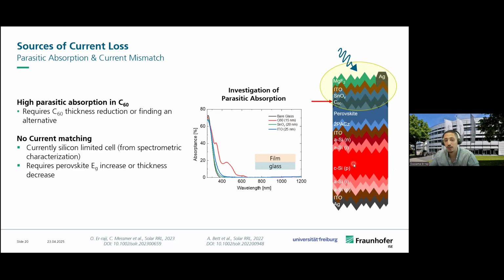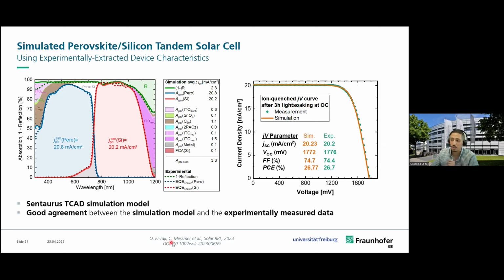So what can we do after we have this thorough characterization of our device? We can then compile all this data and feed it to a certain simulation software that allows us to derive what the next optimization steps are. This is what was done by my colleague here, Christoph Messmer, using Sentaurus TCAD. He was able, using the extracted device characteristics, to have a very nice fit of our experimental device. Here you see it in green, and then the simulated curve is in orange. And you can see also a nice fit between the experimental optical data and the simulated one.